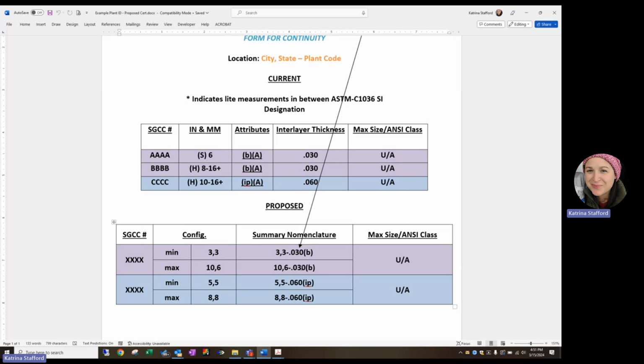This allowed SGCC to take the two SGCC products. Since they both were tested to 030, they both were a PVB, and we made one product. Therefore, with this construction, you will be able to make any configuration with one light between 3mm and thicker, because you have no cap since this maximum was tested to 10 with an 030 interlayer. And your second light can be between 3mm and 6mm, the 6mm being capped. Keep in mind, to have a 16 plus designation that allows you to make anything thicker, you have to submit at least 2 lights of 8mm glass. This will allow you to certify to have no cap on the maximum configuration that you can use.